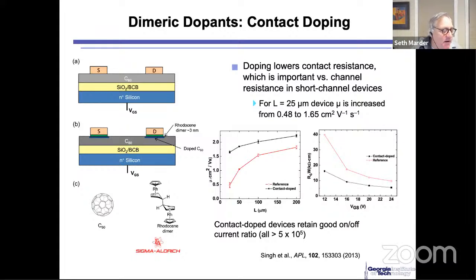I think that I may not be understanding you correctly, but when you say that you're changing the Fermi level pinning, at some level those are one and the same thing, okay? The trap filling is moving the Fermi level up, and so you are in fact changing the Fermi level. That is what the trap filling is doing. It's basically pushing the Fermi level up, towards the transport levels. So would you say the injection barriers have changed as well in that plot that you showed? Likely, and that's what I'm going to show on this slide specifically.